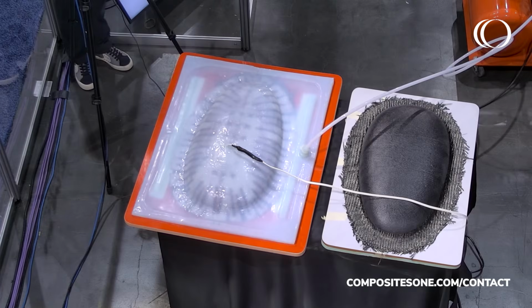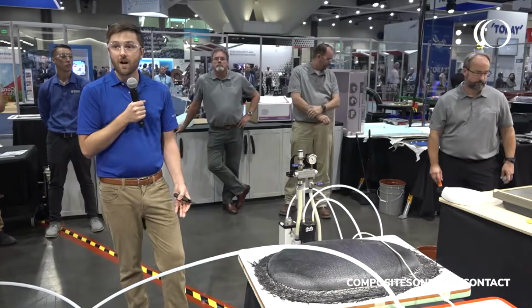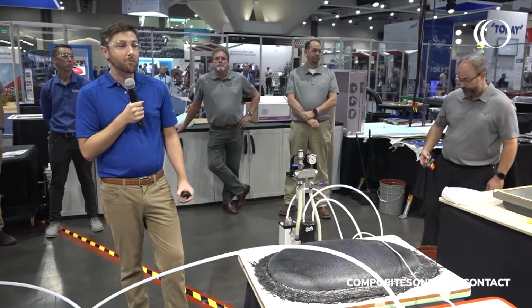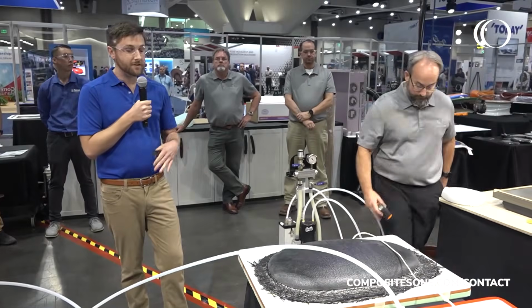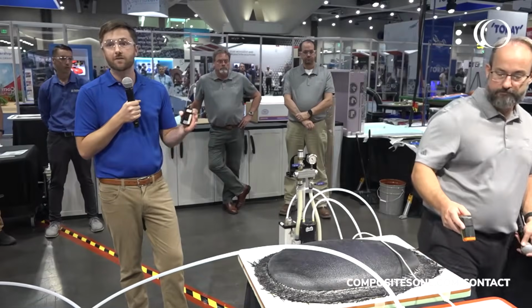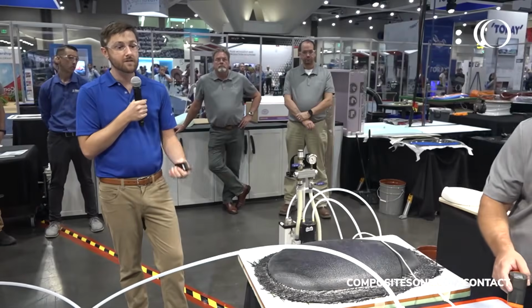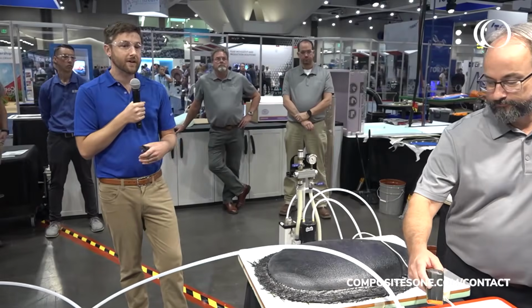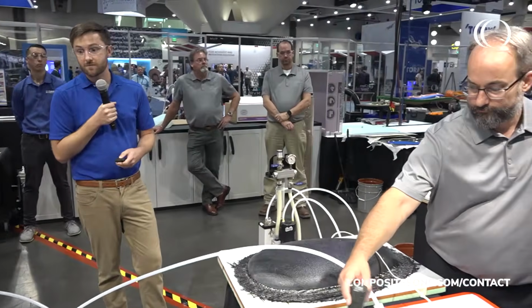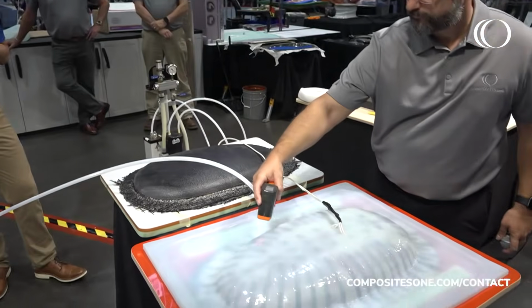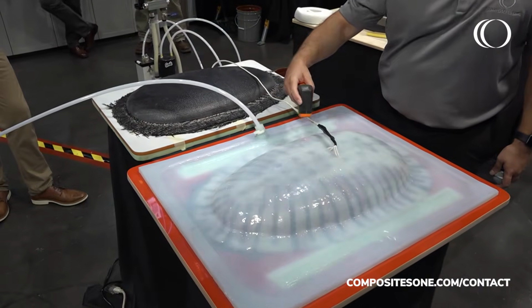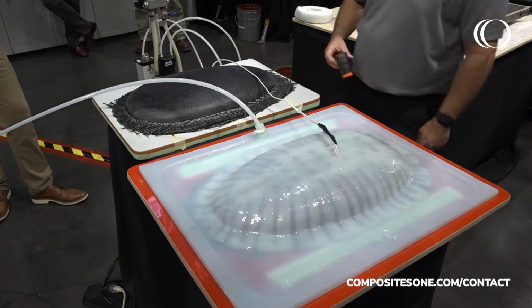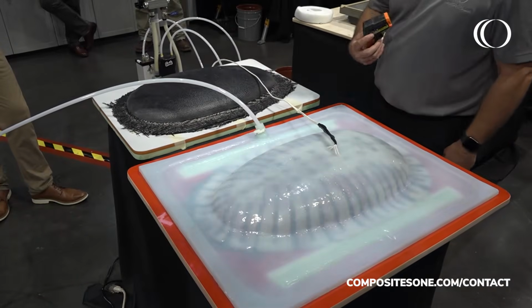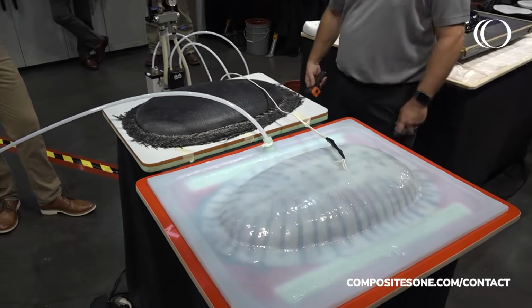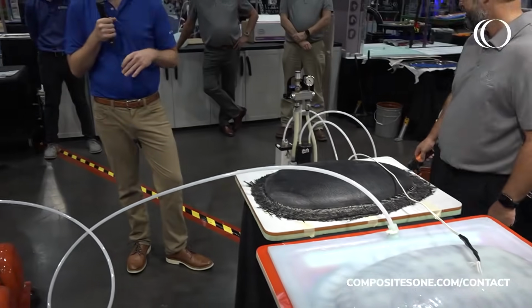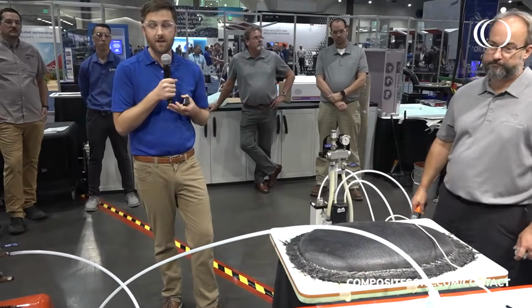It's also highly infusible, and that's again because it is triaxial in a single layer. Our bias fibers span from the top down to the bottom of each ply, and that creates through thickness resin infusion channels that allow air to evacuate easily and the resin to be infused. It's also great, the fact that it is quasi-isotropic means that there's no rotated plies needed. It's the same in every direction around. Which means that you don't have to rotate plies and all of the scrap associated with doing that.